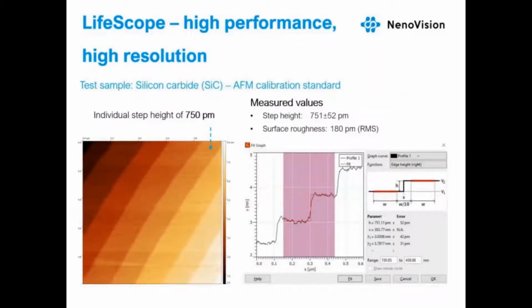And at the end of this part, I would like to demonstrate the performance on a silicon carbide sample, which is an AFM calibration standard. As you can see, we were able to easily measure individual terraces, and we demonstrate the high performance of LifeScope with a height noise level of 50 picometers and a calculated surface roughness of 180 picometers.